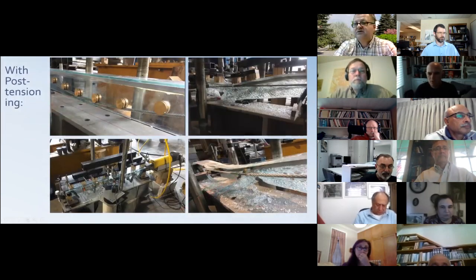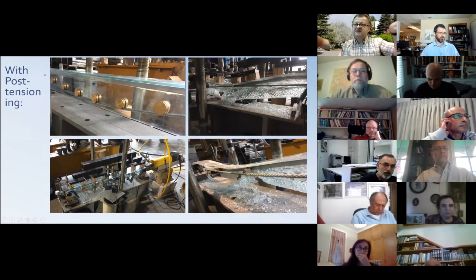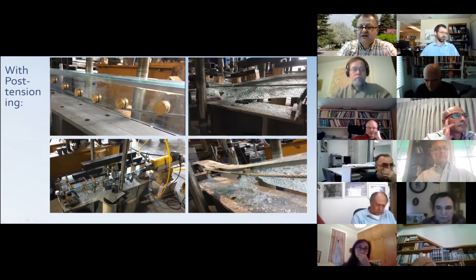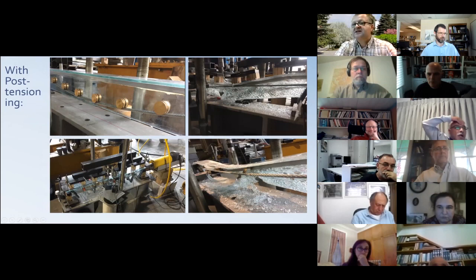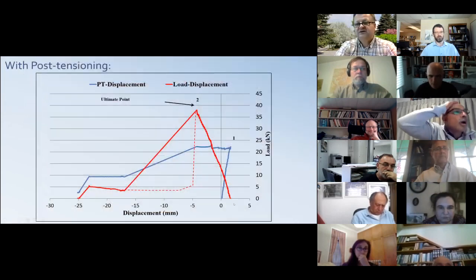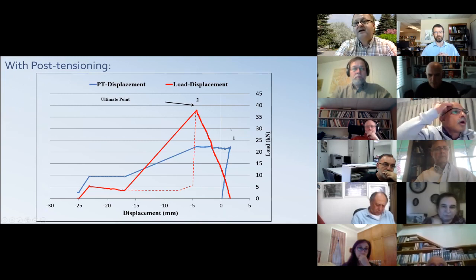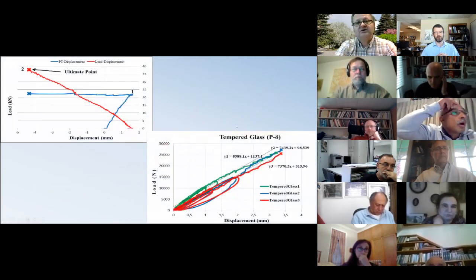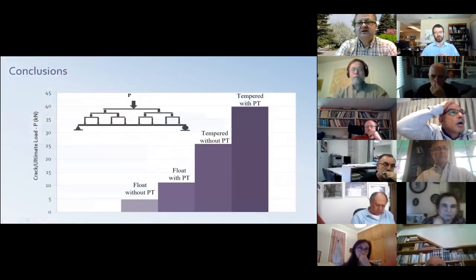The post-tensioning we applied using brass brackets that we have epoxied, and we used this nice curved shape, and we applied the post-tensioning with a hydraulic piston here, and this is after the test. Now, this is the loading during the testing, and I think I need to come to the conclusion.